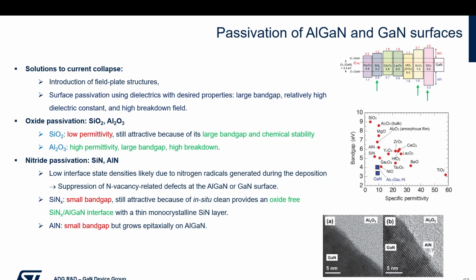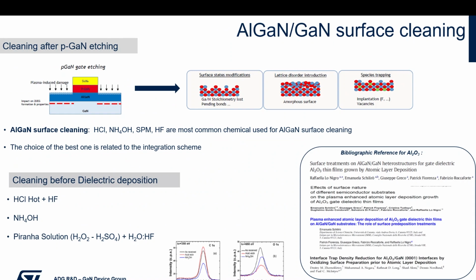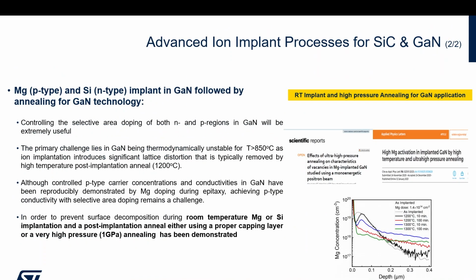Finally, and I'm going to conclude, and I don't have the time to go into detail, there is the passivation. Of course, the way in which you passivate the layer and you close the traps at the interface is very important. And here, the use of high-k dielectric, or the use of atomic layer deposition, is becoming very, very strong compared to the application that we have of the same methodology in silicon or even silicon carbide devices. So I think I can stop here.